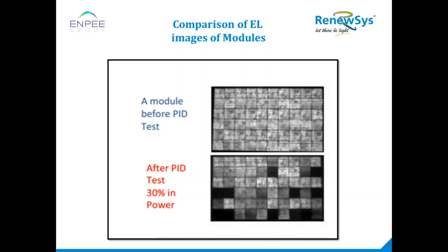See, certification is a process where some third party says whether this module is PID free or not. But other than that, we can use a climatic chamber, where the modules are kept inside a chamber where the temperature is around 85 degrees and humidity is around 85% RH. The other way to check PID is to have a copper foil,